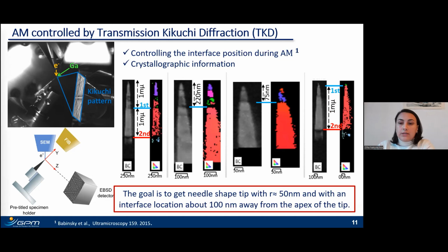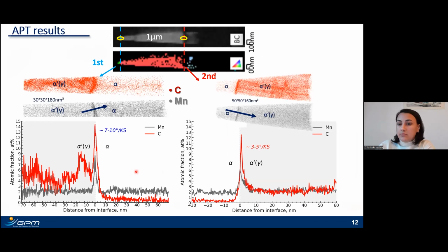Therefore, it is necessary to do the first APT run for the first interface, stop it, and then repeat the same annular milling procedure controlled by TKD for the second interface. This procedure is a bit challenging because there is always a risk of tip fracture during any step of manipulation, but the obtained result is worth it. And if both APT runs are successful, we can obtain the following result.